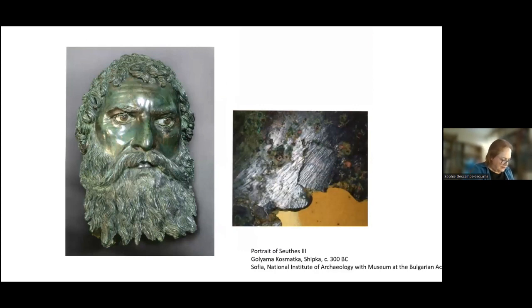Once again, the head of Seuthes III to show you the coating. Because unfortunately, the yellowish brightness of a bronze lasted for a relatively short period of time, for the metal is unstable and corrodes quickly. It was necessary then, as I said, to try to slow down the alteration process, that is to say, the natural corrosion of the copper alloy, which is inevitable because it's due to the exposure to air and variation in humidity.